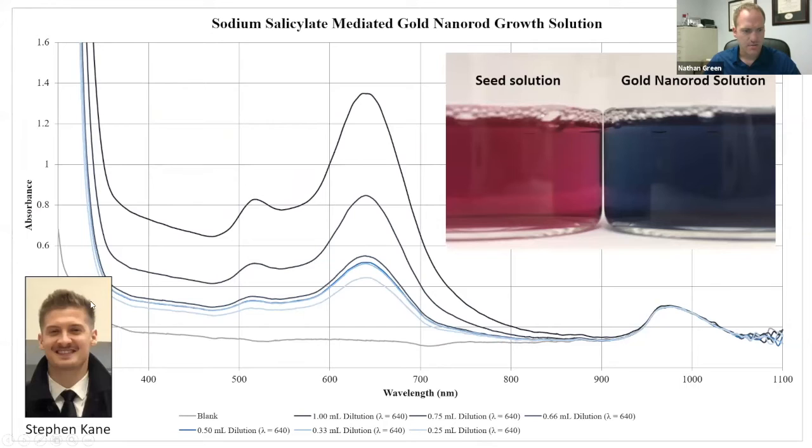So I will, to the best of my ability in here, give credit to my students who have pioneered this for me. Stephen Kane was an undergrad who really helped set up my lab when I first got here about 4 years ago. And he came up with the process we were using, that we still use to this day, to make gold nanorods. And so you can see here the seed solution that I was talking about has kind of a reddish color. Those are really small particles, and so they look kind of red. As you feed the seed solution into the growth solution, the spheres start to turn into rods, and you can see this second peak start to develop. So this is the transverse peak, and this is the longitudinal peak.